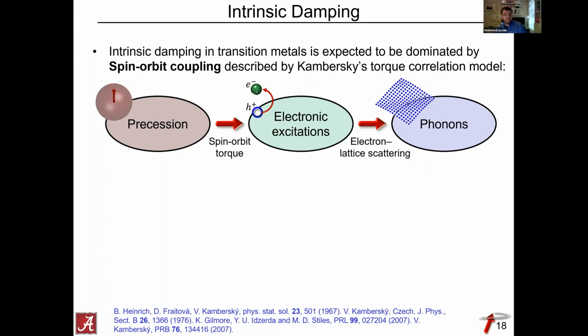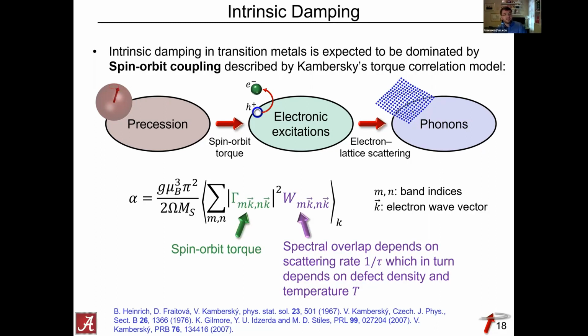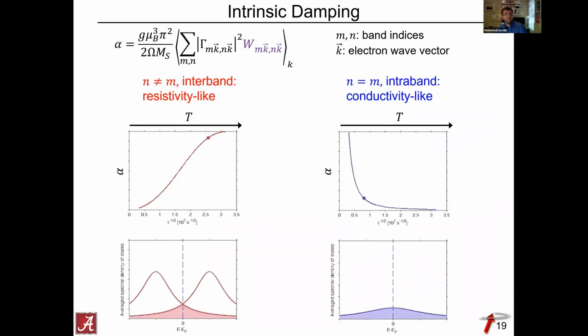You can obviously describe that mathematically. I don't want to go into the details, but essentially you have this spin-orbit torque here, and you have the spectral overlap, which in turn depends on the scattering rate, which itself depends typically on the temperature. Let me give you a little bit more insight here. There are two main contributions that we consider when we talk about spin-orbit coupling. They have to do with whether you scatter between bands, where the band indices are different, so n is not equal to m, so that's an interband contribution to the spin-orbit damping.